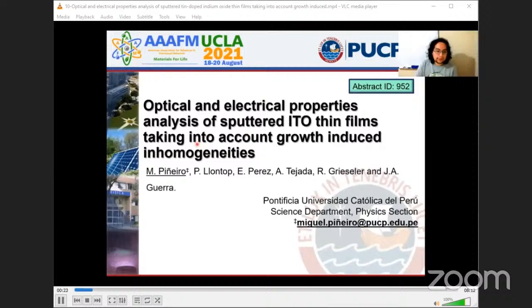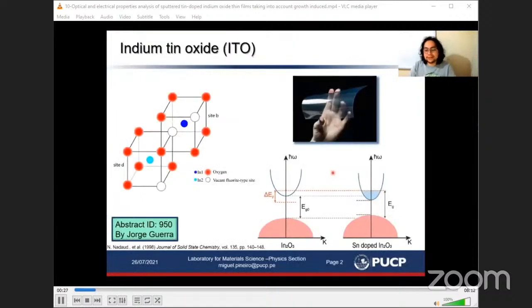taking into account growth-induced inhomogeneities. ITO is the most intensively studied transparent semiconductor because it shows high transmittance in the visible region and low electrical resistance. This low electrical resistivity is due to a higher carrier concentration because the Fermi level in the energy band diagram is located above the conduction level. This degeneracy is caused by substitutional tin which occupies indium sites. This affects a distortion of the bixbyite structure and allows the formation of oxygen vacancies. These defects, substitutional tin and oxygen vacancies, contribute charge carriers in the conduction band and explain the good conductivity.